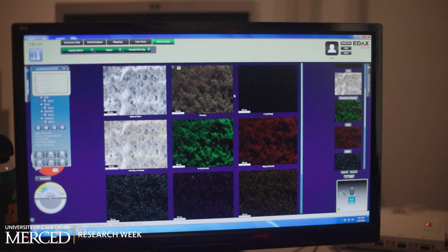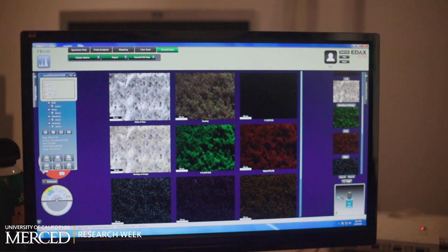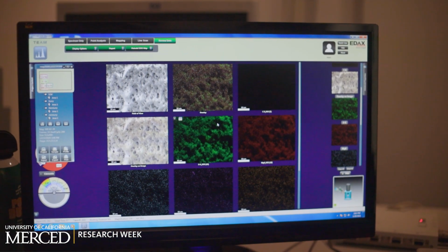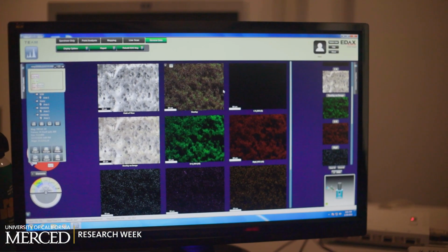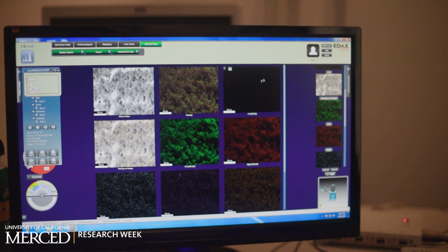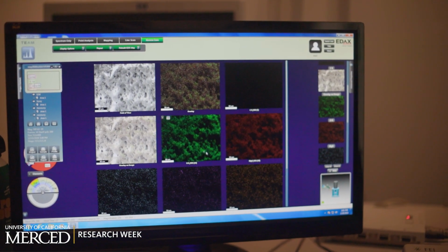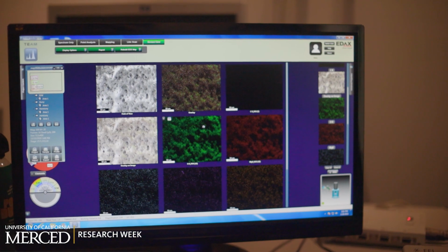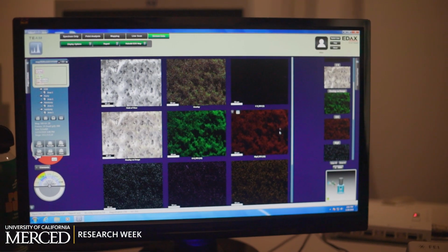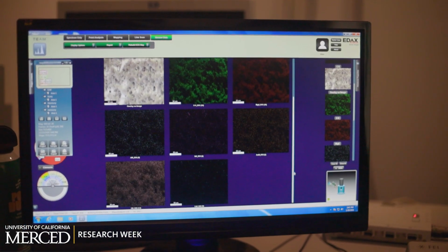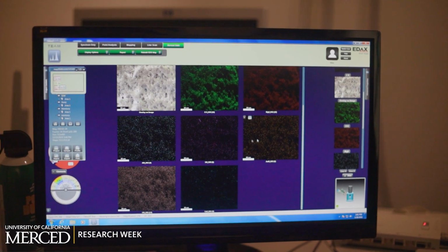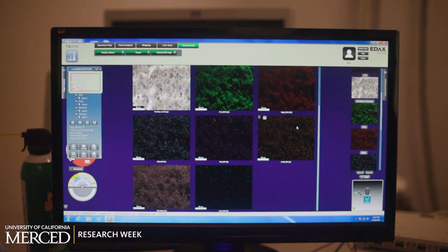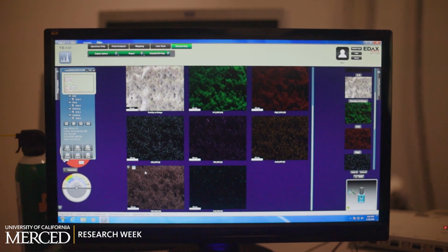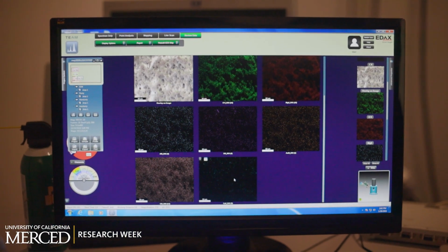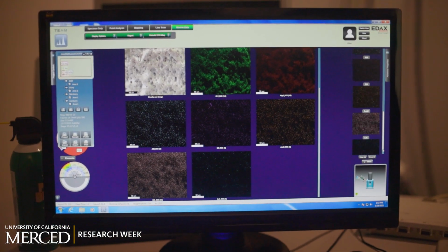So this is a map I did before. This is a view of the sample, and these are the different elements, showing spatially where each of them is. You don't see a lot of carbon, since it's light, so you don't see the signal. You see oxygen. This is where the oxygen is located. Magnesium, and you can see aluminum, silicon. Some of these don't have as much signal, but they're there. For the calcium, you'll see a lot of shadows right here.